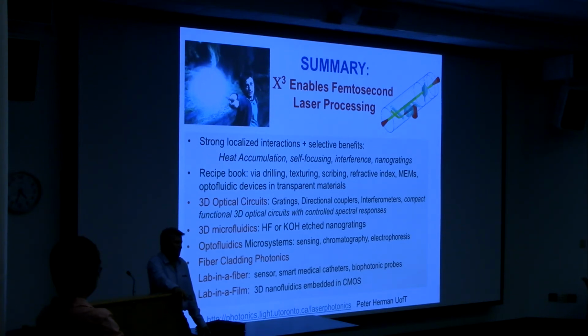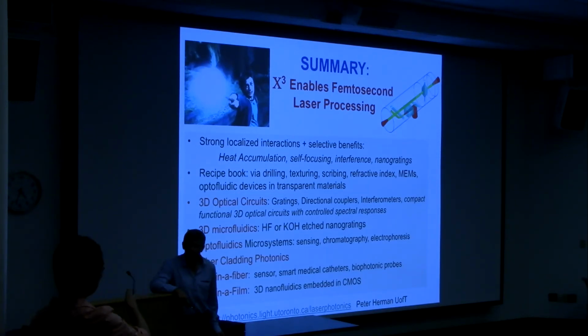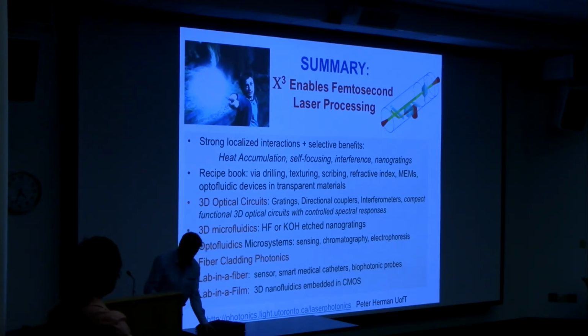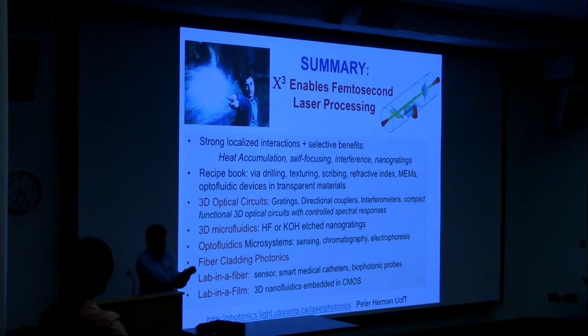I'm sure it's important. So what about the sidewalls for the device you have made inside the fiber? How flat is it? Yeah. So the writing laser focuses down. When the polarization is like this, these planes assemble this way. These surfaces are quite flat, to say 10 nanometers, maybe 20 or so. Locally, over small areas, they're 10 nanometers, so really amazing. But on the bottom, they're maybe 200 to 300 nanometers roughness, so submicron roughness. That's because at the end of the planes, the morphology is more abrupt.